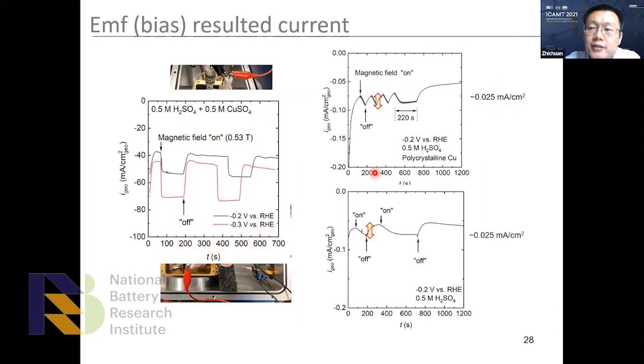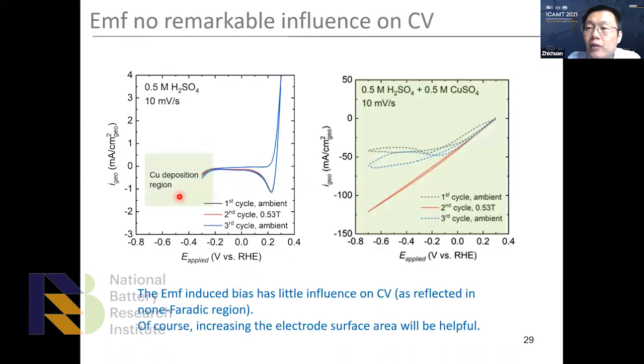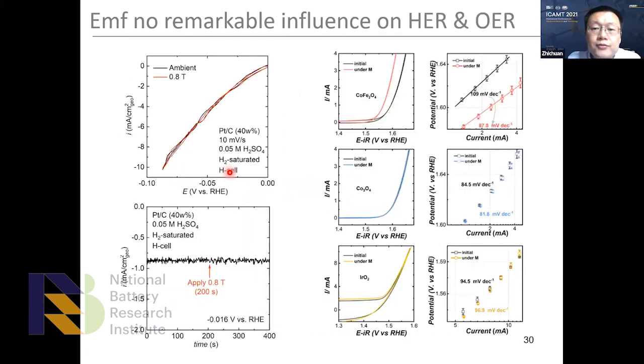However, if we make the electrode big enough, we can see the current change affected by the magnetic field is actually much bigger, maybe 100,000 times the magnetic difference over there. So the bias induced by Faraday's law can actually be minimized by using a bigger electrode. That is exactly what we are doing here. And based on the CV, we can see that the Lorentz force and the Faraday's law induced bias actually had little influence if we use the CV approach. And this is the same thing here.